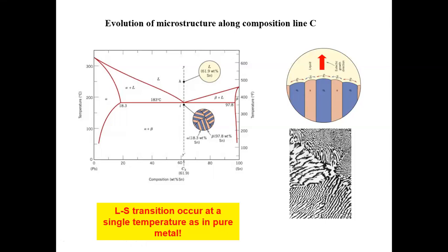rationale. That's why you're going to see this eutectic microstructure, which is composed of very thin stripes of alternating alpha and beta phases. And the thickness of the stripe is basically diffusion controlled. We'll analyze this later. It's controlled by diffusion temperature. Okay, but this is, you can imagine, right? This is a very efficient way of separating the tin and lead into different regions. You just do this in the nearby region. You don't do long-range diffusion. You just repel what you don't want to nearby regions. So it forms this alternating stripes. Okay.